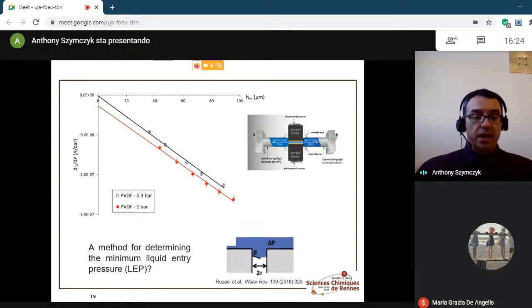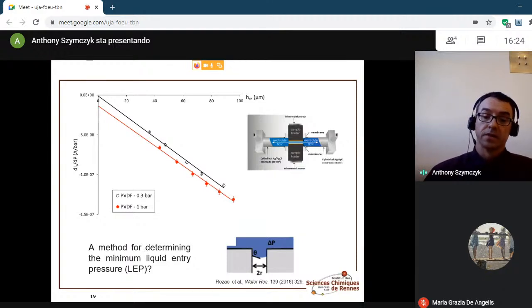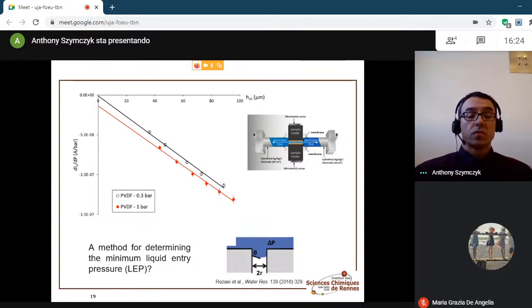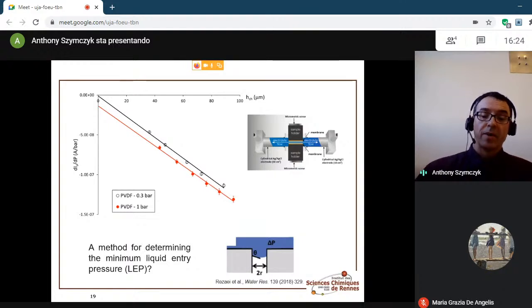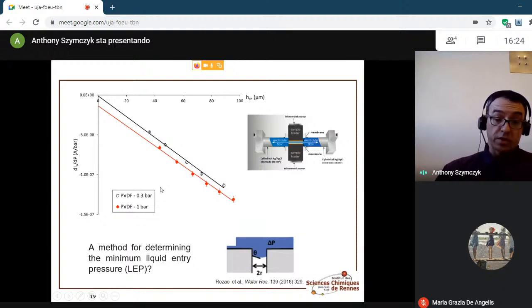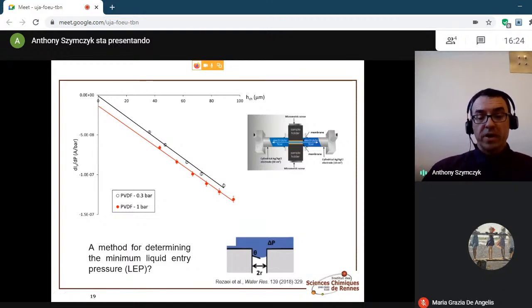All right, the next slide shows the results obtained by carrying out the same type of experiment, but this time with a PVDF ultrafiltration membrane. The measurements were carried out with the same sample, but applying different pressures to circulate the measuring solution in the streaming channel. When the measurements were carried out by applying a pressure difference of 0.3 bar, no electrokinetic leakage was detected. This is most likely due to the relatively hydrophobic nature of PVDF, which prevents the entry of liquid into the membrane matrix. However, if the experiment is repeated, this time by applying a pressure difference of 1 bar within the system, then a slight electrokinetic leakage occurs and is detected.